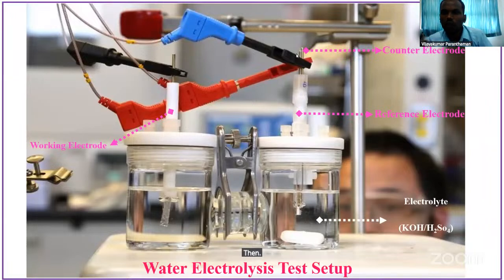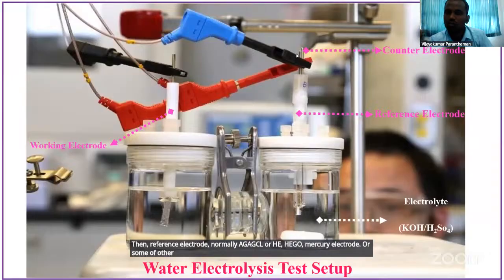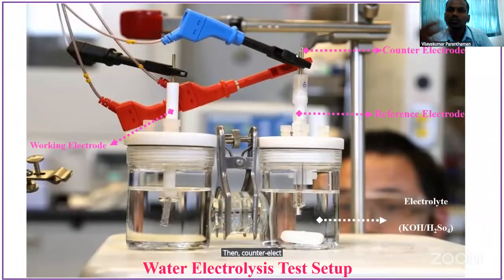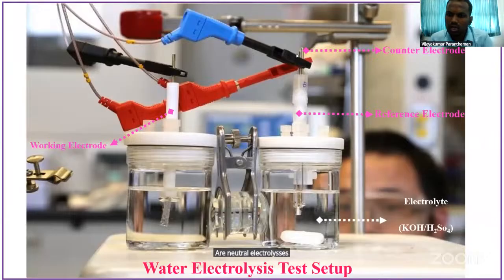Then for the reference electrode, normally Ag/AgCl or Hg/HgO, mercury electrode is used, or some other reference electrodes are also used. Then for the counter electrode, you must use platinum sheet or platinum wire, or some other counter electrodes like graphene counter electrode, which some of the papers used. The water does not conduct electricity spontaneously. So we use electrolytes like alkaline, acid, or neutral electrolysis, such as KOH, H2SO4. For this work, we have used KOH, the alkaline electrolysis.